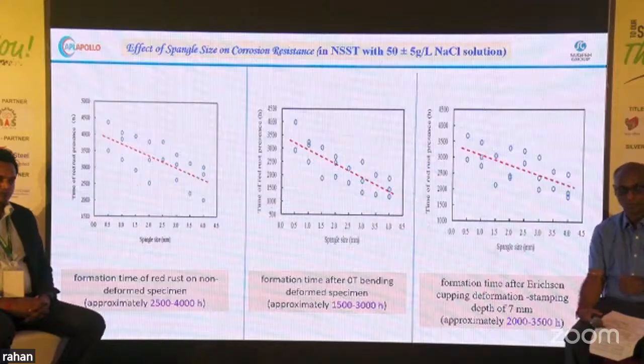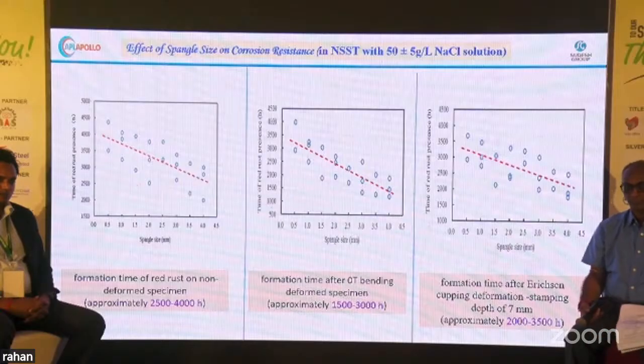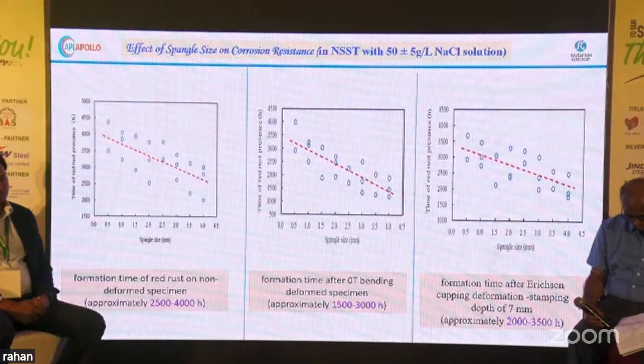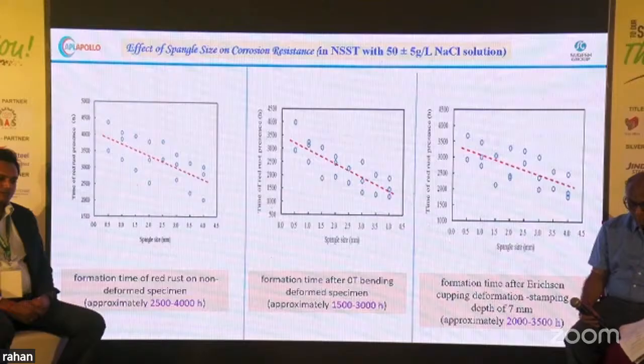In the middle, we are doing forming and bending applications, for roofing or trapezoidal sheet making for roofing purposes. Here also the same thing is happening, though the corrosion rate is more with respect to the undeformed state. But here also, lower and smaller spangles give a more corrosion resistant product. On the right side is the Erichsen cupping test for drawing application. Here also the same phenomenon is happening. We are getting up to 3,500 hours when we decrease the spangle size.